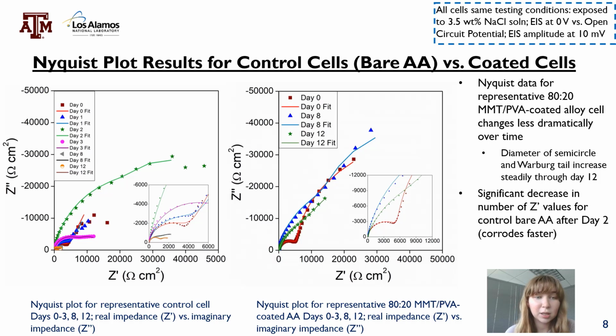If we take a look at the left-hand graph in the zoomed-in version, the semicircle phenomenon can most easily be seen in days 3, 0, and 12. However, if you take a look at the right-hand graph, zoomed-in version, this semicircle is most prevalent in day 0. The Warburg tail is the part of the graph which extends out of the semicircle towards increasing Z double prime value. The takeaway from these graphs is that the Nyquist data for the representative 80-20 MMT PVA coated alloy cell changes less dramatically over time.